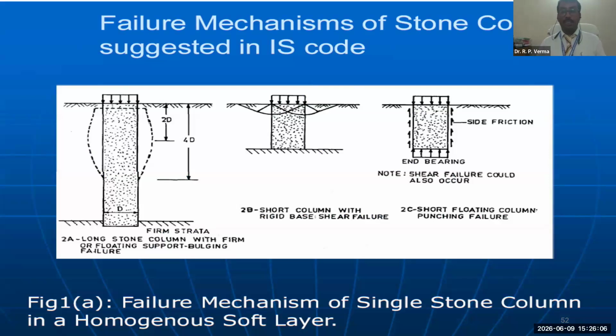The Indian Standard Code highlights three principal failure modes for a single column in a homogeneous soft layer. Figure 2a shows a long stone column with firm or floating support. It fails via bulging, typically occurring within an upper zone of 2 to 3 column diameters, where lateral confining pressure from the weak soil is lowest.